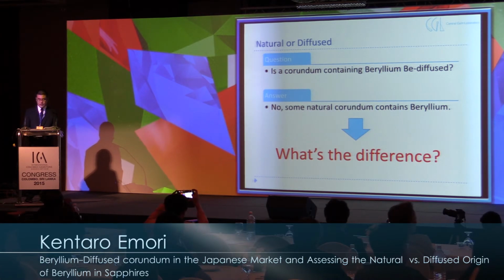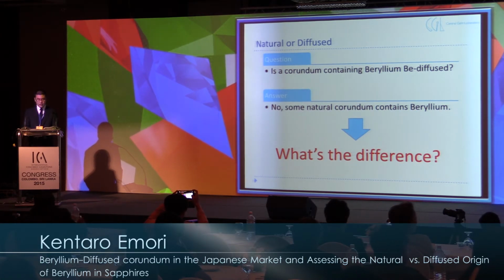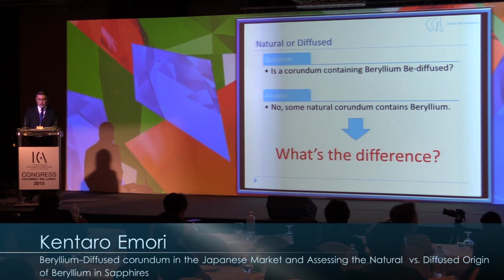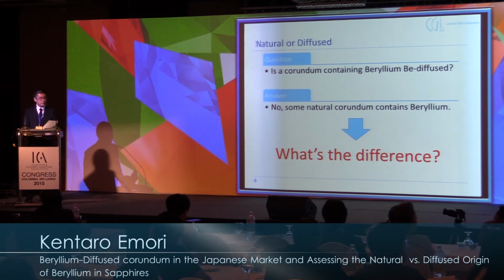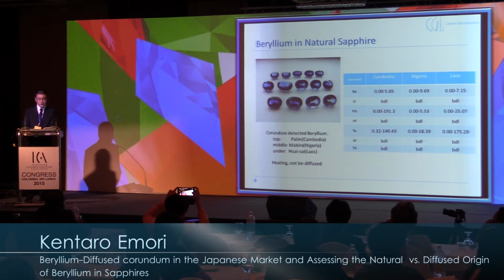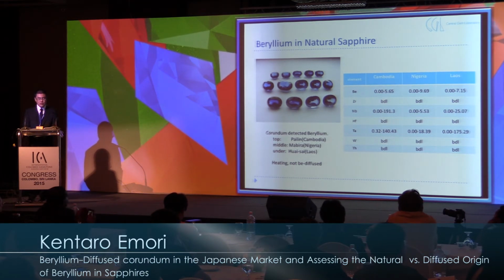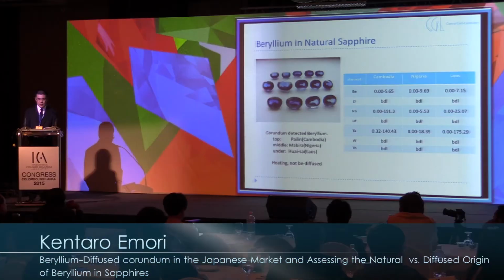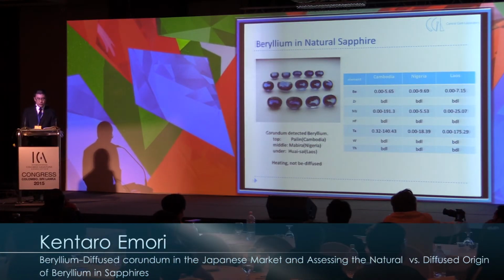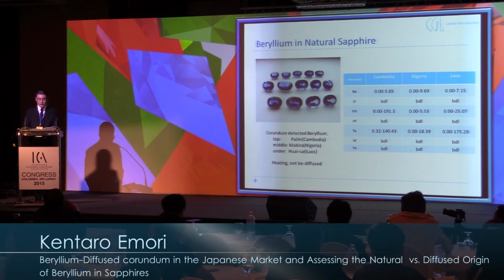What is the difference between them? A little technical talking, I introduce the result of non-treated corundum containing beryllium. The example of sapphires containing natural origin beryllium is shown here. These are blue sapphires of basaltic origin from Huaisai in Laos, Pailin in Cambodia, and Mabira in Nigeria. In addition to beryllium, niobium and tantalum were detected in these samples. The contents of these elements are shown in this table, and they are traces.